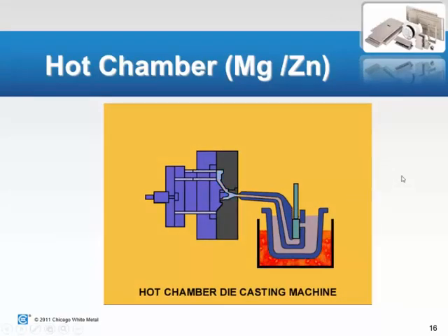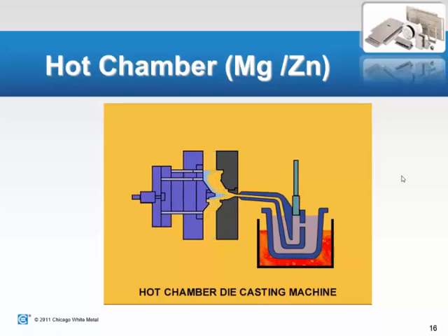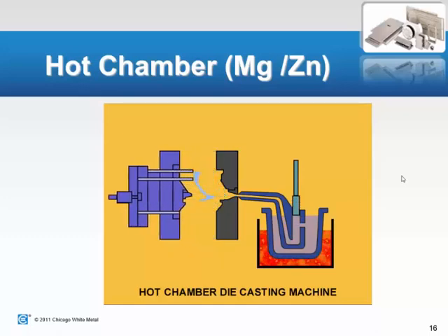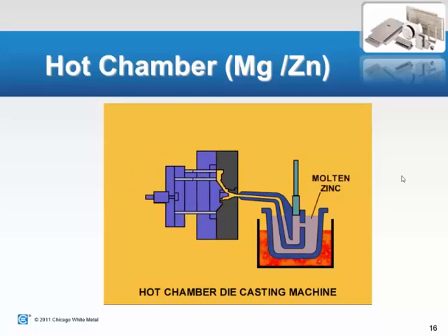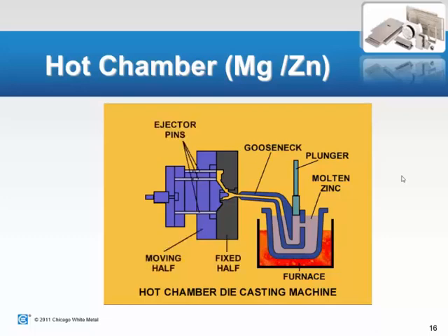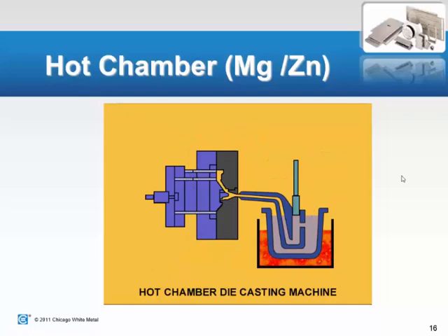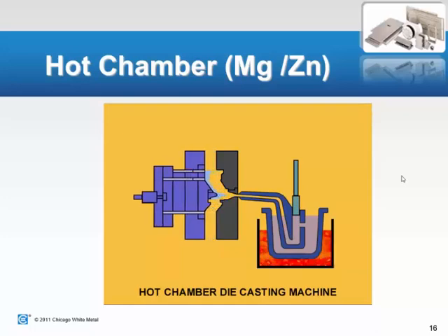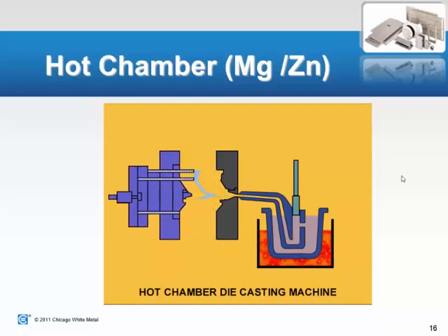Here you can see the hot chamber animation. Again, it's very similar. The biggest difference between hot chamber and cold chamber is how the metal is physically injected into the die. In this view, you can see the injection system is physically inside the molten metal. So the metal is never exposed to the atmosphere as it is injected into the die. The lower temperature alloys, such as zinc and magnesium, can run this way because it's not as aggressive on the injection system, and that is why it's buried inside there.